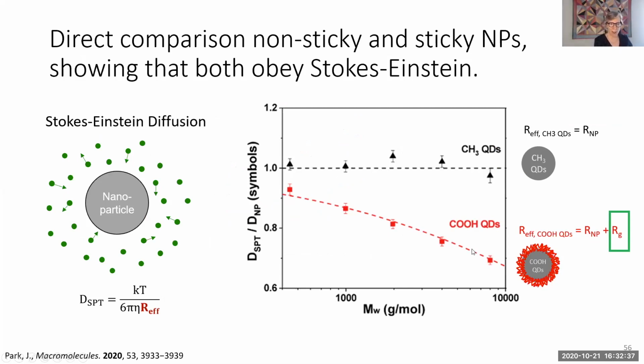So this dashed line now is the Stokes-Einstein approximation where we're using R effective. And R effective is the core nanoparticle size plus Rg. And so Rg increases with molecular weight, of course. And actually it goes as molecular weight to the half because we're in a polymer melt. And so that's how the modified Stokes-Einstein fits with this dashed line. And in the case where it's a non-sticky particle, then we just use the core particle because there's no polymer sticking to it, and that captures the data, right? This is just the diffusion coefficient relative to the Stokes-Einstein with the bare particle.